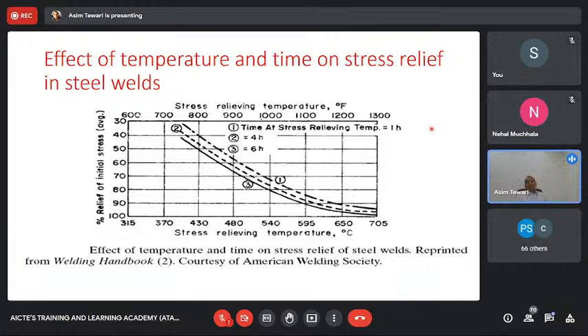Effect of temperature and time on stress relief in steel welds. Now welding has a lot of literature, and all these problems of porosity and residual stresses and distortion exist in welding. Additive manufacturing is actually nothing but a more glorified welding topic. Now over there, the effect of temperature and time on residual stress is very important. Why? Because once you expose a welded structure or an additively manufactured structure to a high enough temperature for a long enough time, you'll start seeing that the stresses decrease themselves.